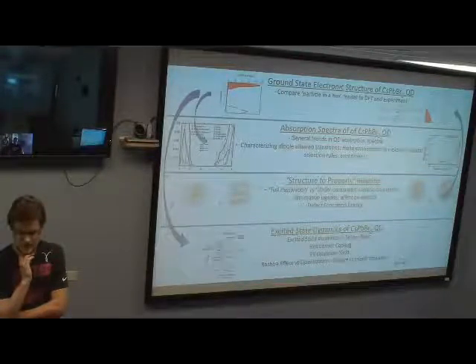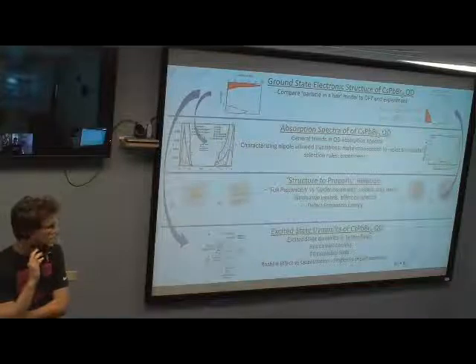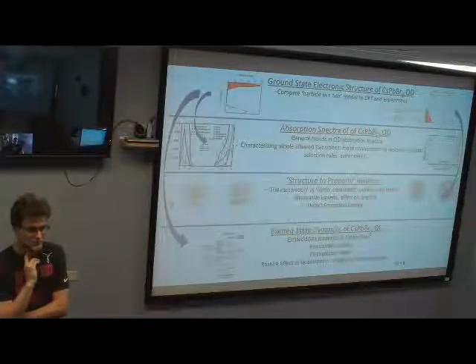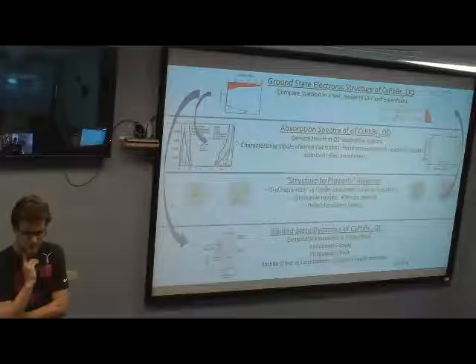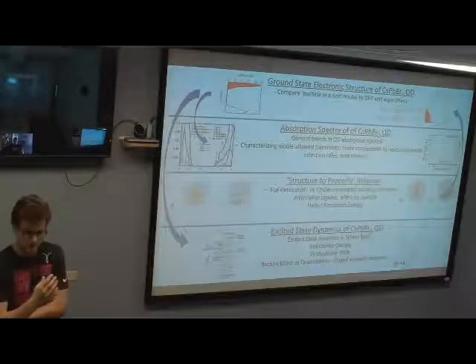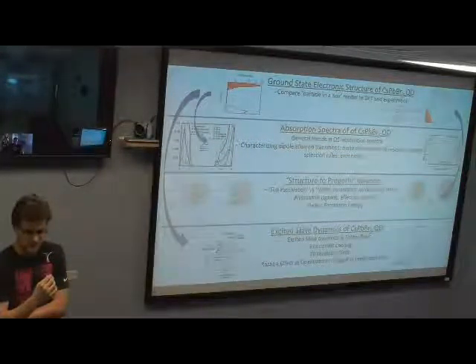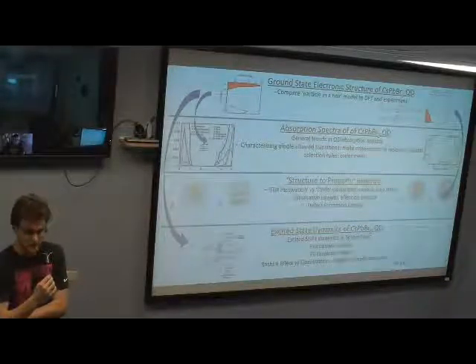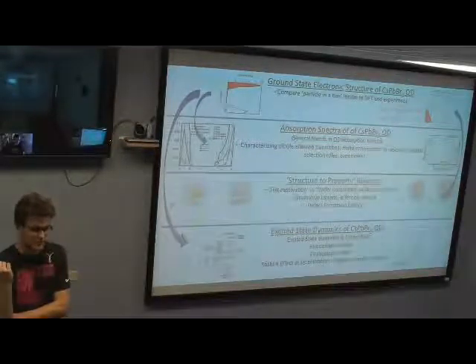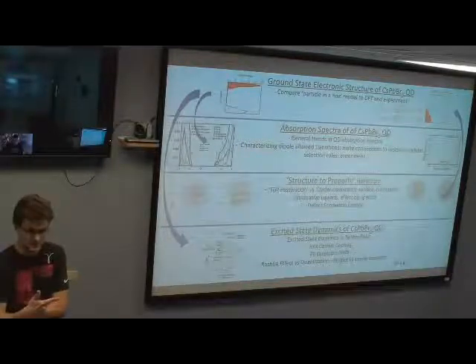So in terms of the excited state dynamics. I guess I didn't put it into the presentation, but I was just refreshing on some of the literature, and bulk perovskites have very slow hot carrier cooling, which is useful for solar cells, because you want slow recombination. But in quantum dots, they see sub-picosecond, around 200, 300 femtosecond relaxation rates. People are trying to understand whether it's Auger effects, phonon processes, or ligands, the mechanism of this quick relaxation.